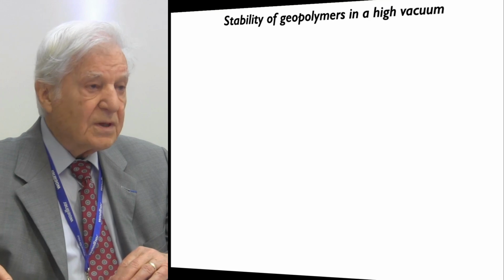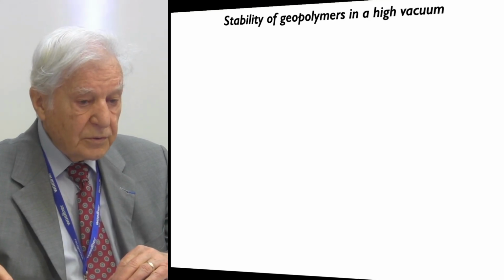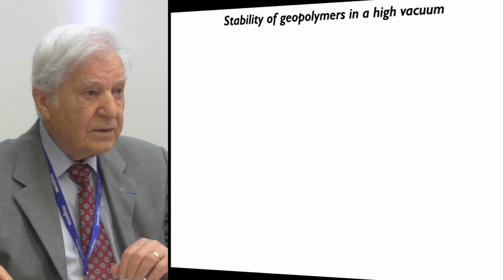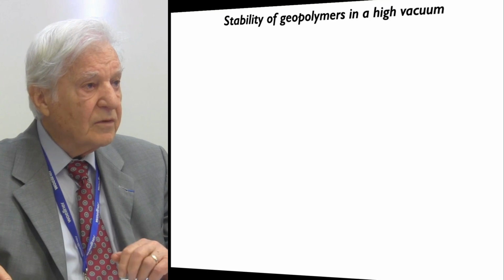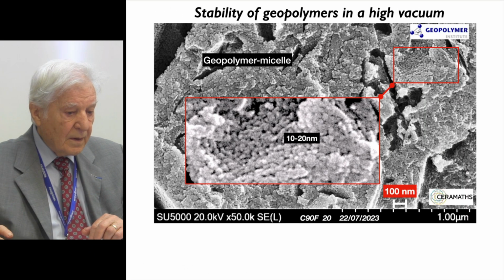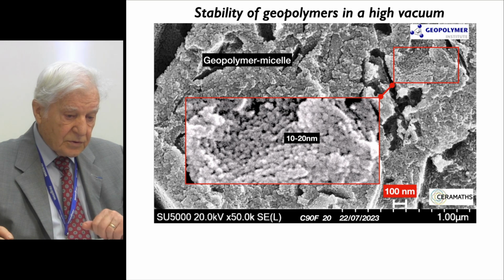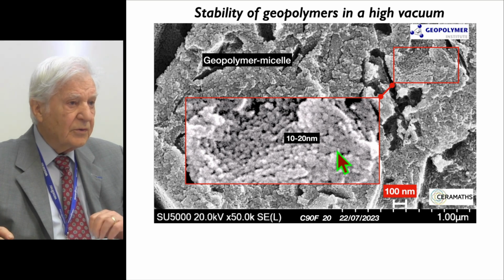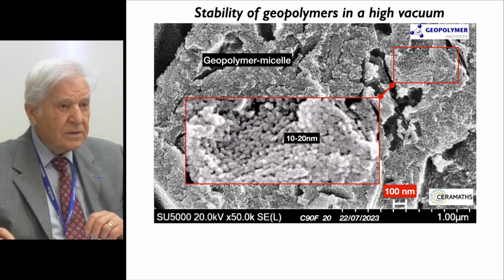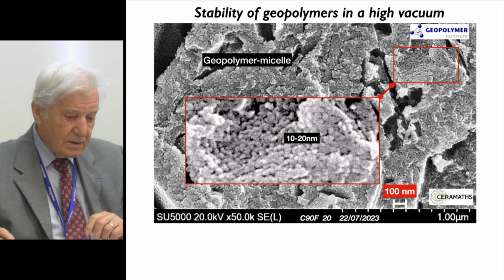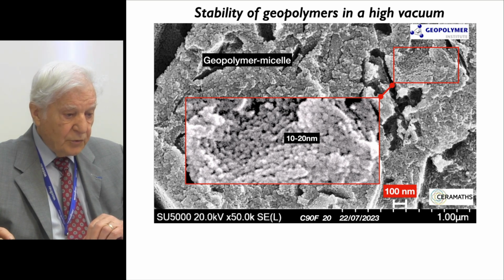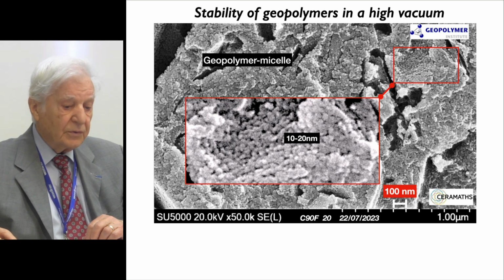There are several reasons for the stability of geopolymers in a high vacuum. The quaternary structure of the geopolymer micelles is well defined, and I presented this in my keynote on research and development yesterday. Geopolymer binder consists of these amorphous nanoparticles, and the enlarged view on the screen shows beautiful geopolymer micelles with overall dimensions in the range of 10 to 20 nanometers. Fillers, such as regolith sand and fine aggregates, are mixed with the geopolymer micellar binder system to produce composite materials, cement or concrete, that exhibit all the physical properties that I will now develop in this keynote.